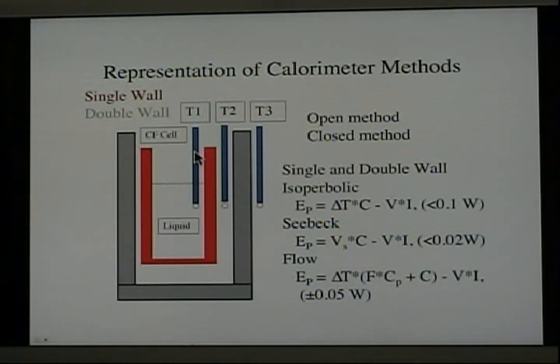The single-wall isoperibolic calorimeter was the one that was used by Pons and Fleischmann initially, and it's the most simple of the four. It consists of measuring the temperature within the electrolytic cell, and measuring the temperature outside of the cell to get the temperature drop across the cell wall, which is proportional to the heat flow. The outside temperature is easy to measure because the cell is usually in a constant temperature bath. The problem comes in measuring the temperature inside the cell.